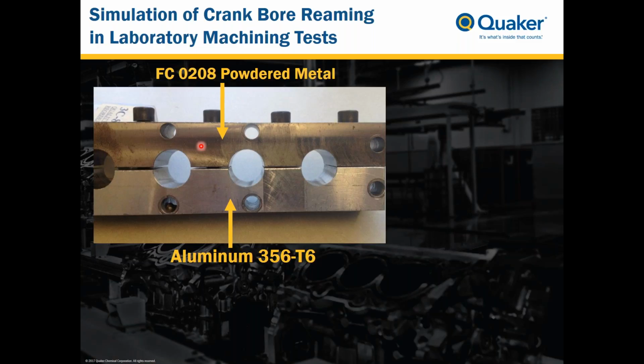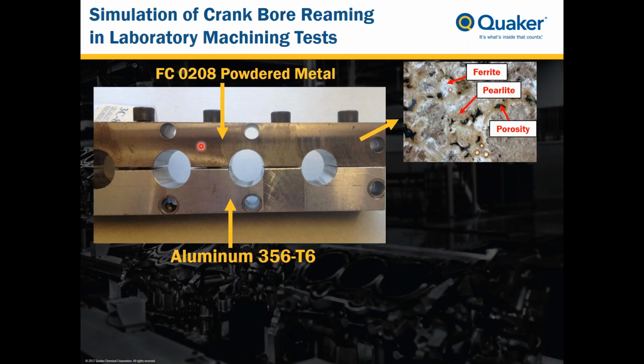It's primarily iron. It has 2% copper and a little under 1% carbon. And shown here is the microstructure, photograph of the microstructure of this material. And very characteristic of powdered steels, you can see the very distinct regions of ferritic material. You can see the high pearlite, which gives much of the strength to the powdered metal.